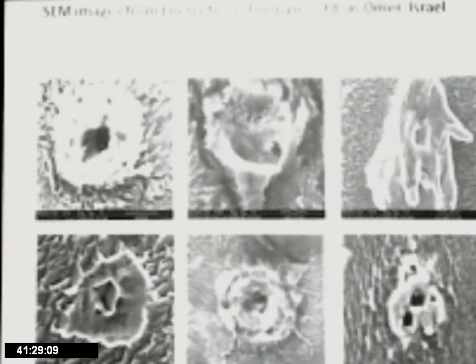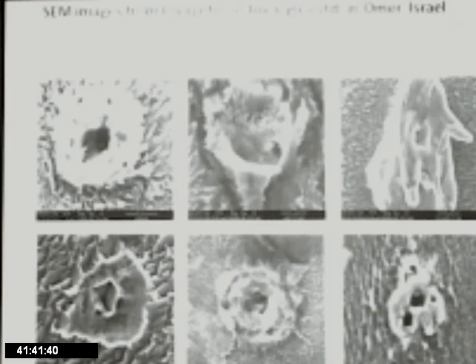Now, these are images that got people pretty excited at Energetic Technologies. These are pits that they saw only in the cathodes that produced high excess heat results. I asked if they had done any broad area survey to see the pitting and the size of the pitting and see if that correlates with the observed excess heat result. They had not done that work at the time. I believe they're trying to do that sort of thing now.